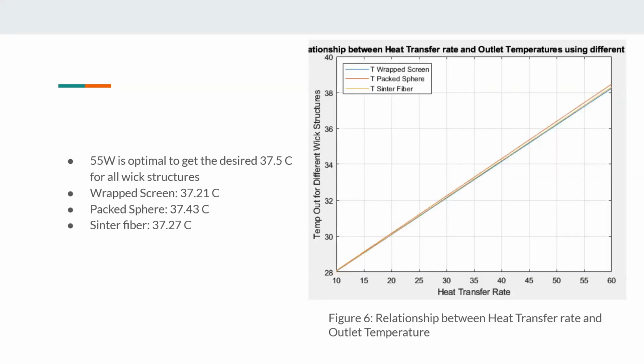Here we see that 55 watts would be the optimal heat transfer to get what was desired, 37.5 degrees Celsius. This was true for all of the different wick structures. You could see here that at 55 watts, the outlet temperatures were 37.21, 37.43, and 37.27, which were all very close to the desired. Now for the next slide.